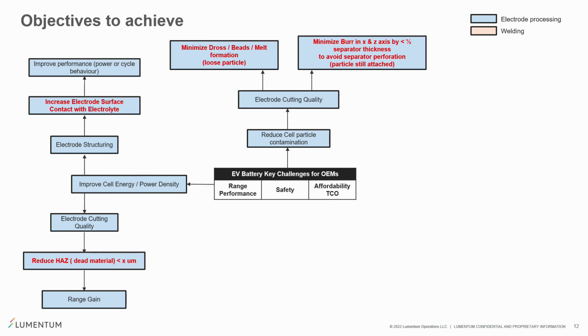Safety, the second factor as well for OEMs. And the gigafactories typically have to address that point by reducing particle contamination. To do that, again, it's cutting quality. And there you end up with two families of problems. One is the detached particles, the particles you don't want to end up on your electrode because they will short circuit at some point your electrode. They'll create runaways and make your battery go in flame. And you want to make sure about the burr, which is the particle still attached.